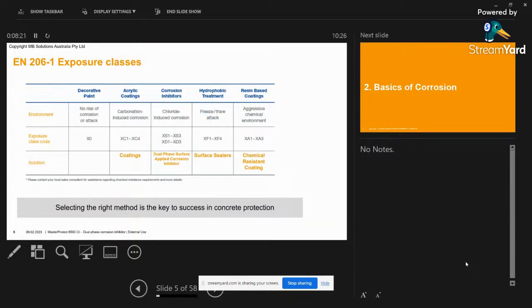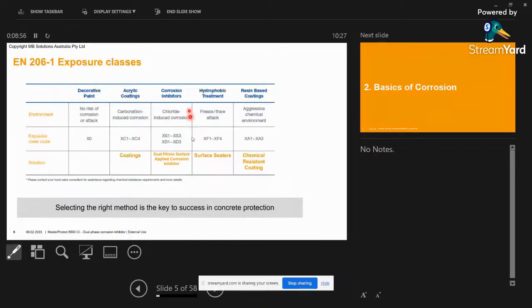If you look at it from the corrosion exposure point of view, the environmental condition has a big influence on the corrosion activity. And that's why, even as per the code, this is an example of an EN code, we have classification of mild, severe, extreme conditions, and so forth. So what we will be talking about here is this system: corrosion inhibitors, which are surface applied, mainly effective for providing a good inhibition of the corrosion in case of chloride induced active corrosion.